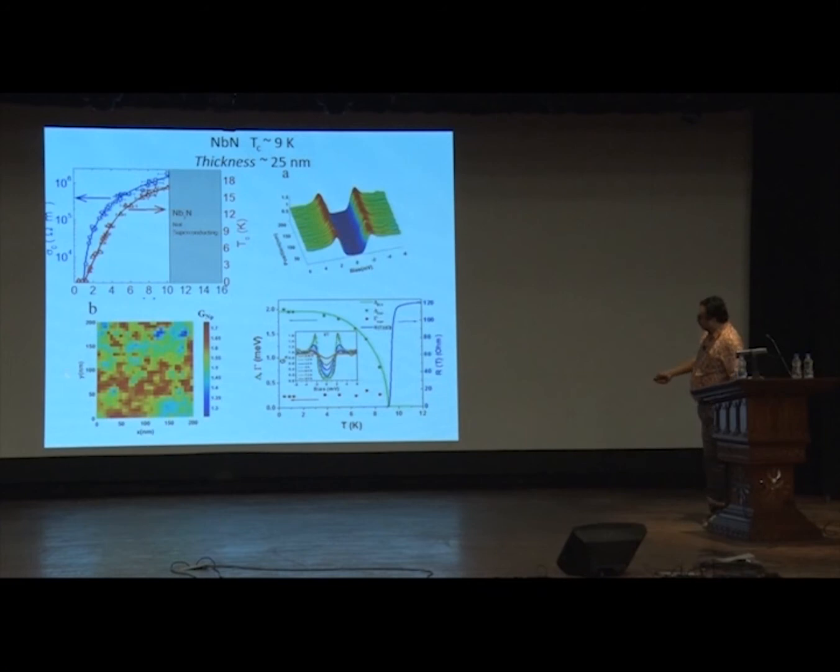And therefore, I have a finite superconducting order everywhere. However, the strength varies. So I have a landscape which is somewhat disordered. Now here, however, if I take the average of all these spectra and calculate the superconducting gap as a function of temperature, what I see is that it follows perfectly the BCS expected variation. So the superconducting gap follows this green line and it drops to 0 exactly at TC, and TC is defined as the point where my resistance disappears in the resistance versus temperature measurement.